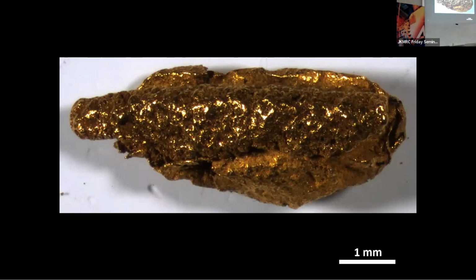So that self-healing aspect of the beach rock, we took that experiment to an nth degree. We grabbed a sample of beach rock, and we chiseled off that surface biosphere, and we hit it with a hammer, and we took it back to sand. Then we took the lower material and bashed it with a hammer and took it back to sand, threw it in one of our little shoebox bioreactors, and Janine had 2 tides a day, in and out, in and out, over a 2-month period.